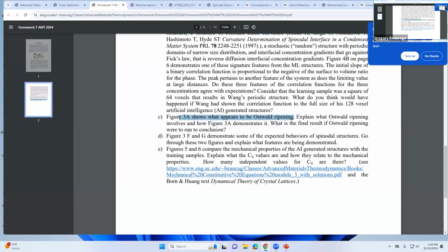Like when you nucleate and you have multiple polymorphs of a crystal, the higher energy one is closer to the liquid energy, so it forms first. So when you nucleate, you get the high energy phases forming first, then the low energy phase, the phase you want to grow, forms second, and it consumes the high energy phases. That's the way Ostwald talked about it originally.